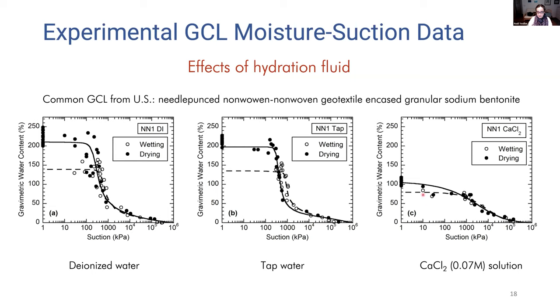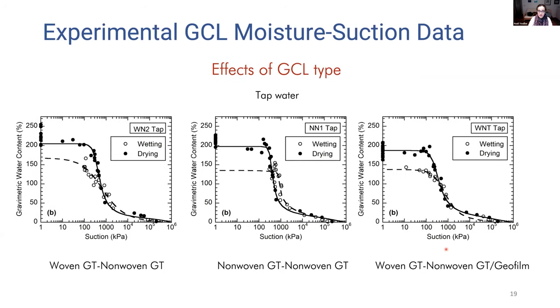The wetting and drying curves both collapse, the moisture contents decrease, the saturated moisture contents are no longer reaching the 140 to 200% or so. We're limited to 100%, the 80 to 100% range or so. Hysteresis is not significant, and basically everything is the same after a suction on the order of 1,000 kPa or so. We also looked at, in moisture-suction relationships, effects of GCL type.